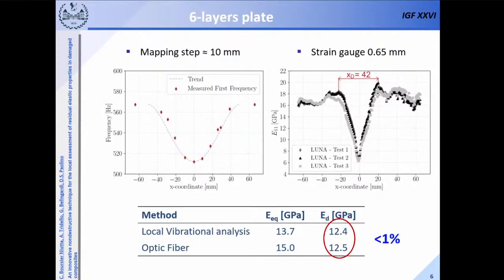And these are the results for the 6-layer plates, where you can see that the reduction of the frequency is proportional to the modal participation of the damage. In particular, the highest reduction is obtained when the damage is in the center of the device. And here from the tensile test, you can see the results of the strains in correspondence of the damage. There is a consistent decrease of the elastic properties. And also by comparing the non-destructive technique with the optic fiber results, you have that the discrepancy is very, very limited.